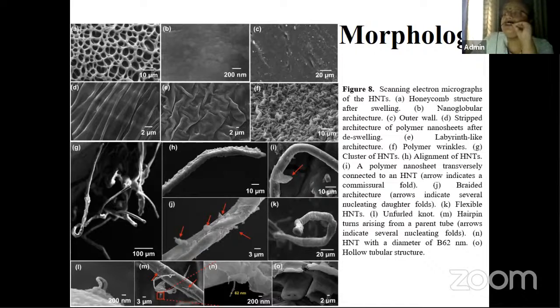So these are the reasons for the genesis of these exotic nanostructures, that is halloysite nanotubes, with the help of the structured water inside forming the ice helix, which has been proved with the help of TEM images and the aliquots taken after every 10 minutes, and also the AFM images. And then we have identified them with several entropic and thermodynamic calculations. And these calculations fit with our images and the experimental results.